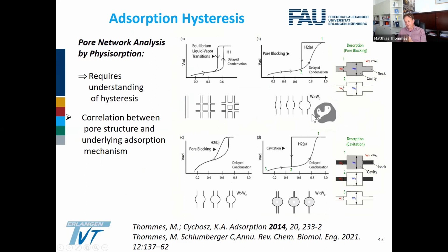Okay, so this explains this asymmetric hysteresis loop. We fill pores according to their size, but during evaporation, you empty the system when you reach a pressure associated with emptying the neck, but then all liquid gets out at once. And that is a classical percolation transition. In this case, we can obtain, as I mentioned, the pore size distribution information from adsorption.